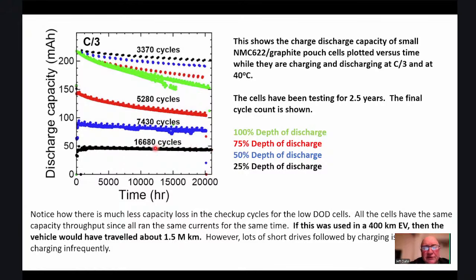Now, the current that is being supplied to these cells is exactly the same for all of them. So all of them have stored and delivered the exact same amount of energy over this time period. And about every 500 charge-discharge cycles, we did a 100% state of charge checkup cycle. So for example, for these black cells, every now and then we did a 100% depth of discharge cycle. So you can see that the black cells retain their capacity much, much better than the green cells do, even though they've stored and delivered back the same amount of energy over the same time period, right? So this shallow charge-discharge cycling is much preferred to the 100% state of charge cycling.